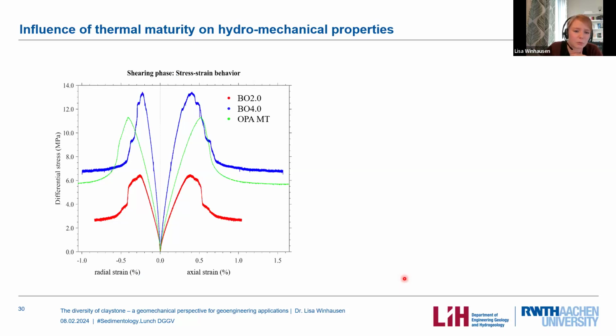So then the last slide, quickly: we have also done hydromechanical tests in consolidated undrained triaxial tests. I will not go into detail here, but you can see again BO2 and BO4. We have a huge difference in strength, so this is when the material fails. We compress it and it fails eventually. I also plotted the Opalinus Clay of Mont Terri under the same experimental and boundary conditions, and it's just in between.